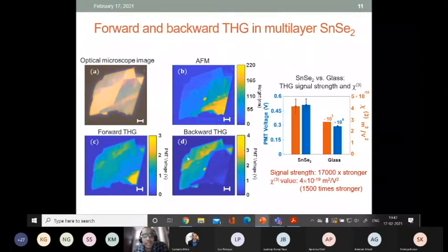What was striking was that the third harmonic contrast looked very different in the forward and the backward directions, which makes it interesting because something to do with how light interacts with the structure is different when light is emitting from the forward or the backward directions. And we also wanted to quantify how this nonlinear material behaves when compared to other nonlinear media.